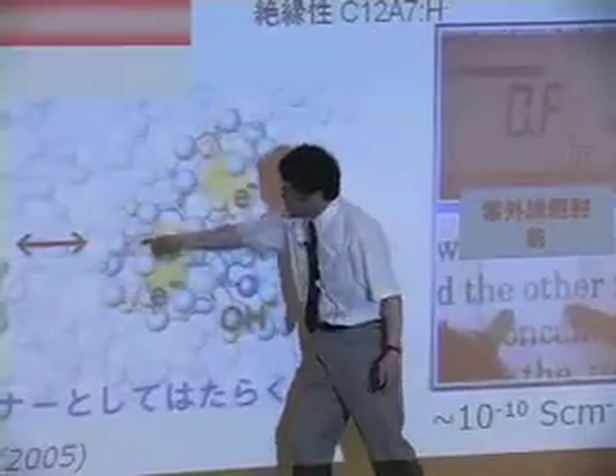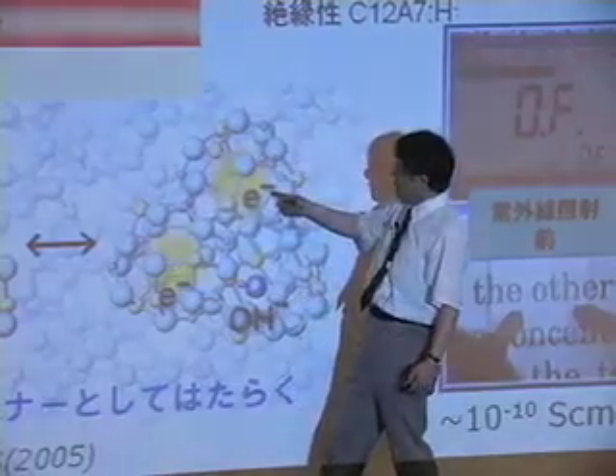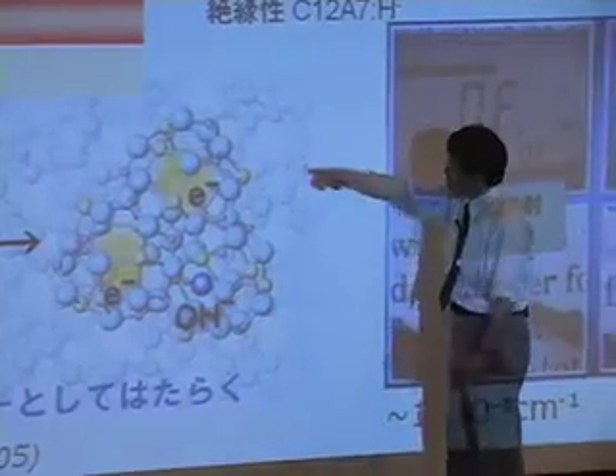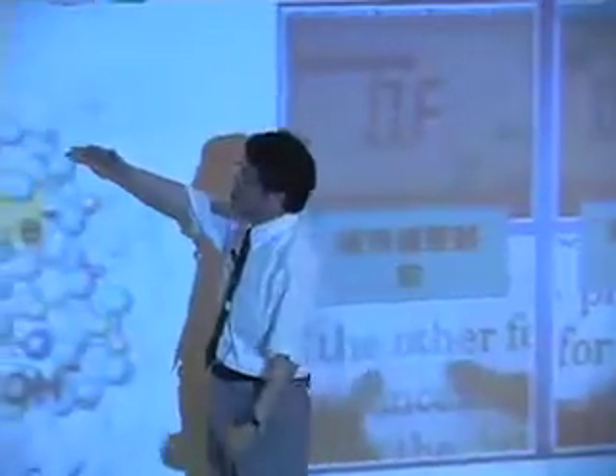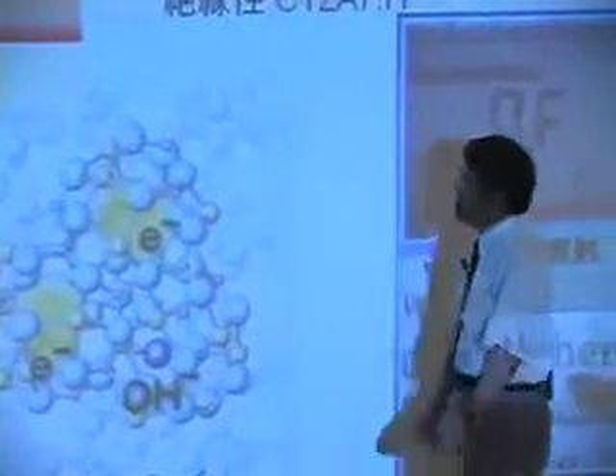So the released electron moves to the vacant cage and hops to nearby vacant cages. As a consequence, we observe electron conduction. When such a conductive state is heated up to 300 degrees C, the reverse reaction occurs, so this reaction is totally reversible.